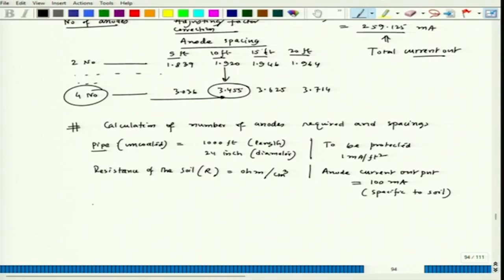So first we have to find out the area and total current requirement. So we have to calculate the number of anodes and spacing for this specific current density that is to be supplied to the pipe. Now, area of the pipe, we can calculate 2 pi r h, 2 into 3.14, 24, into 1000. So 24 is basically in inch. In order to convert into feet, we divide it by 12, and this is the diameter, so we divide it by 2. So this is feet square. So this is the surface area.